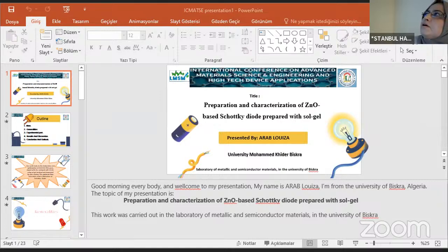The study involved the fabrication and characterization of undoped and doped zinc oxide films with the goal of getting a zinc oxide-based Schottky diode. The films include gallium-doped zinc oxide 4%, and zinc oxide co-doped with aluminum and indium, 4% for each one, and undoped zinc oxide. These films were prepared using sol-gel deposition on ITO and glass substrates, resulting in 7-layer diodes with a total thickness of around 850 nanometers.